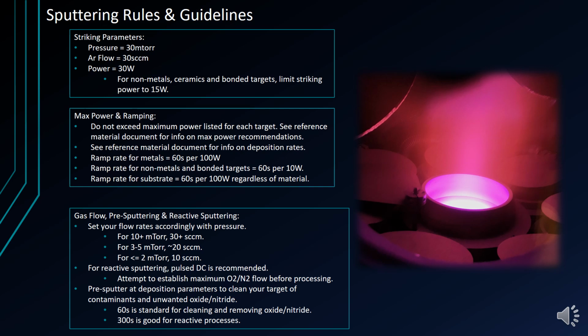Now that we've seen a basic strike and deposit layer, here's some rules and guidelines for creating them. When striking, the following parameters are generally going to work. In circumstances where they do not, there are some troubleshooting tips provided in the Sputter reference material. Pressure, flow, and power can all be set to 30. For non-metals, ceramics, and bonded targets such as silicon and other brittle semiconducting materials, limit your striking power to 15 watts. The reference material lists maximum powers for each material and its target size. Do not exceed maximum power for the respective material.